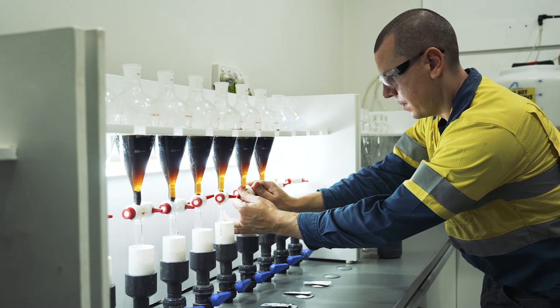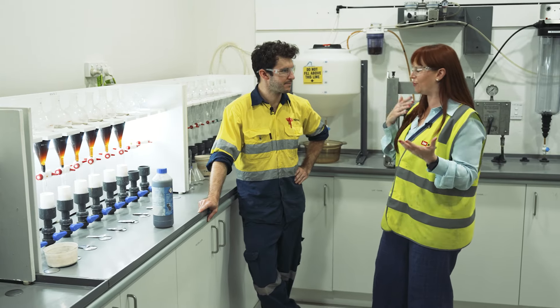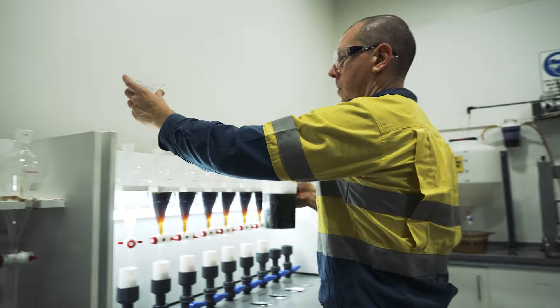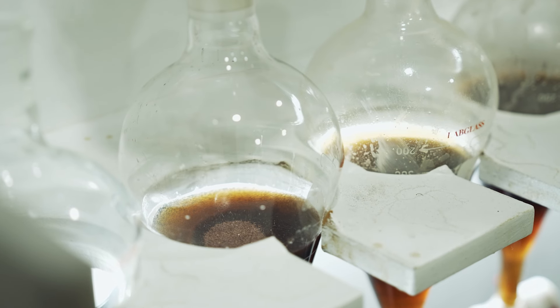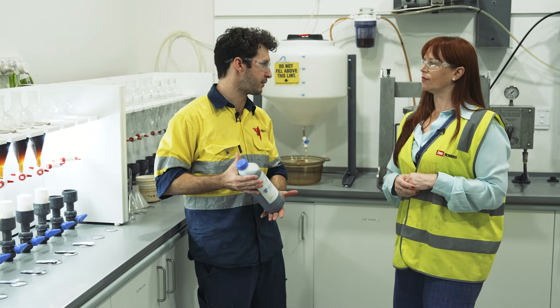We're probably now in the hottest but also coolest room in IHC's laboratory — because it's a bit stifling. This is our heavy liquid separation laboratory. We use a dense medium to separate particles into more dense or less dense. This is the liquid we use to do so, and it needs to be regulated at a minimum of 25 degrees Celsius.